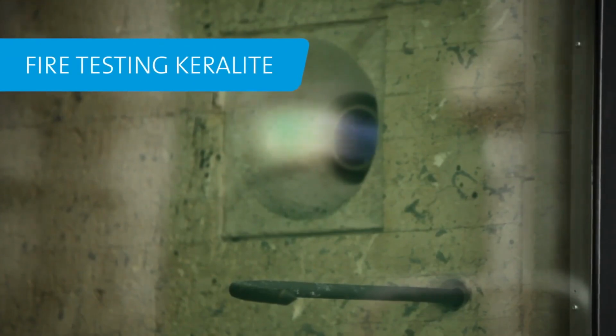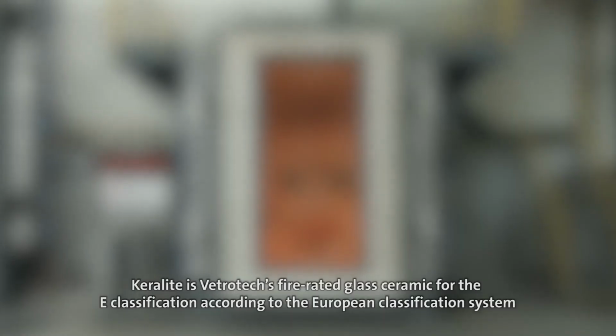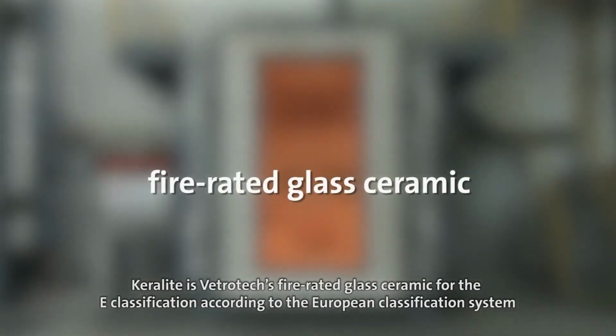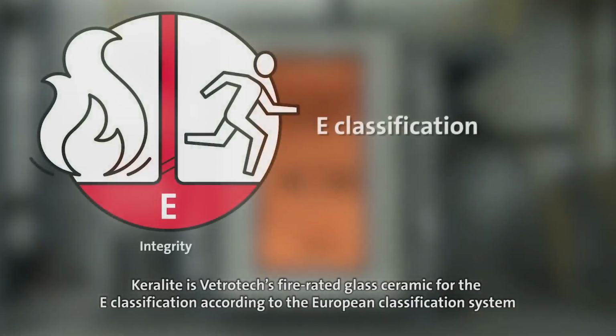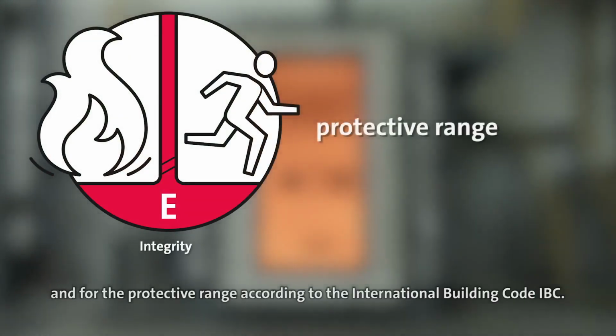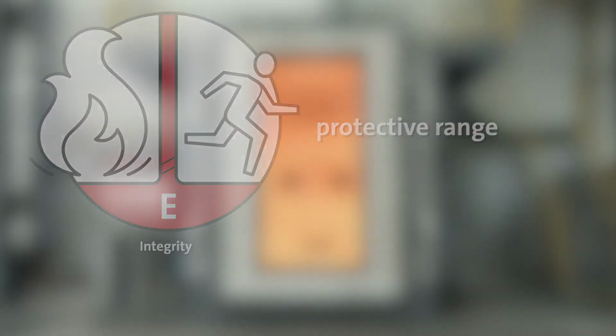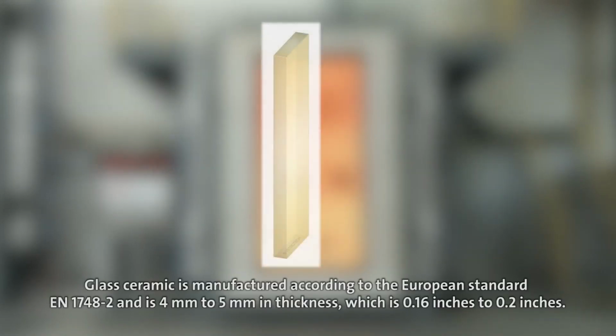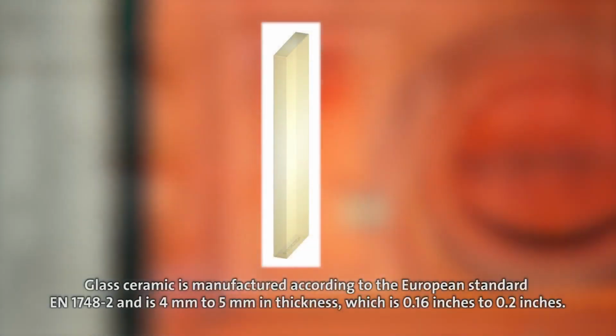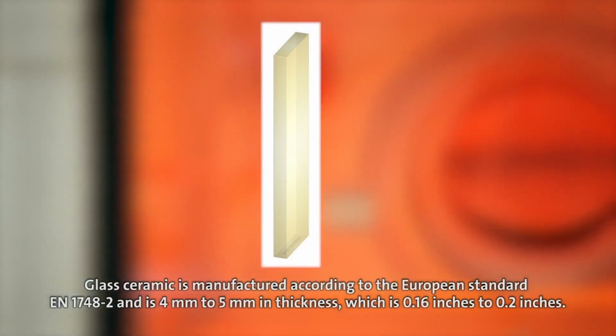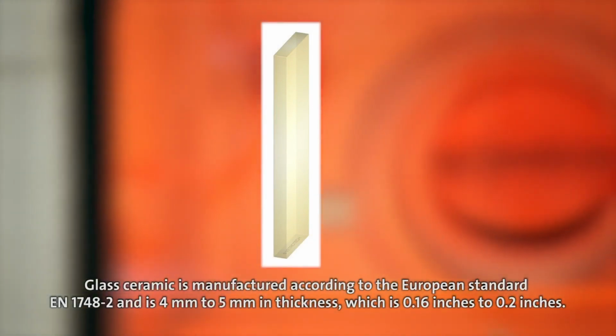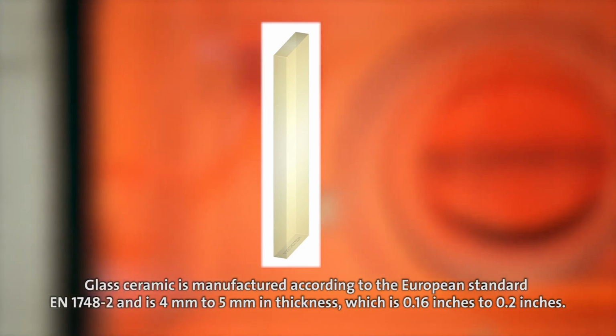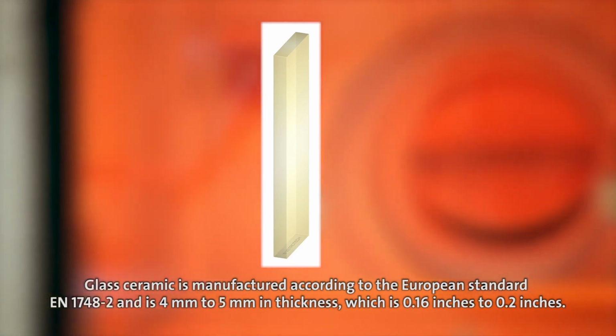Fire testing Keralite. Keralite is Vetrotech's fire-rated glass ceramic for the E classification according to the European classification system and for the protective range according to the International Building Code (IBC). Glass ceramic is manufactured according to the European standard EN 1748-2 and is 4 mm to 5 mm in thickness, which is 0.16 inches to 0.2 inches.